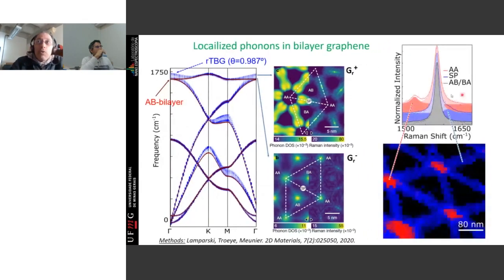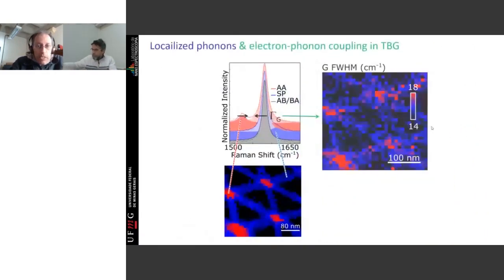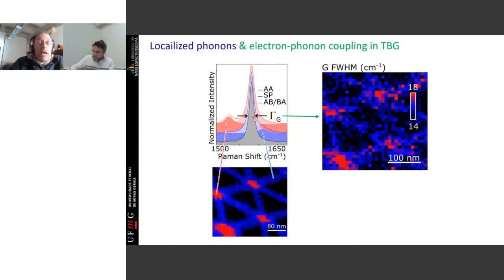And what we do is, when you go with our nano optical system, we see exactly lower frequency phonons localized at the AA sites as predicted, and we have higher frequency phonons localized at the solitons as predicted theoretically. And interesting also is to look at the width of this peak. I was telling you that the width of a peak is related to the uncertainty that you have on the frequency of this peak, okay? And what we see again is that along the soliton lines and in these AA dots, AA points, you have this peak getting broad. So why does it get broad there?